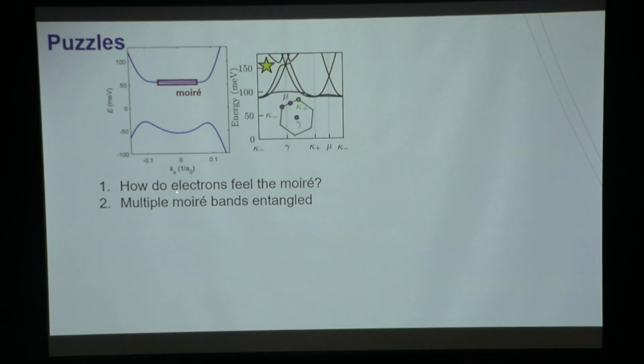For two reasons. Number one, we do have a very flat bottom of the conduction band. But as I was telling you, when we observe this effect, the electrons at the flat band are residing at the side opposite from where the Moiré superlattice is. So how do they even know there is a Moiré superlattice? How do they even feel the Moiré potential and adjust themselves to it? This is not clear. Well, maybe you think somehow there's buckling of the structure, so these electrons can indirectly feel the Moiré effect.